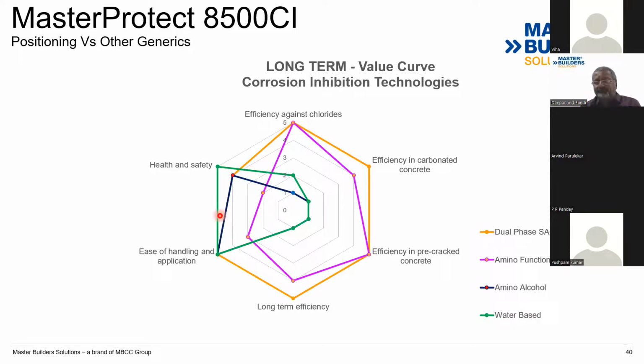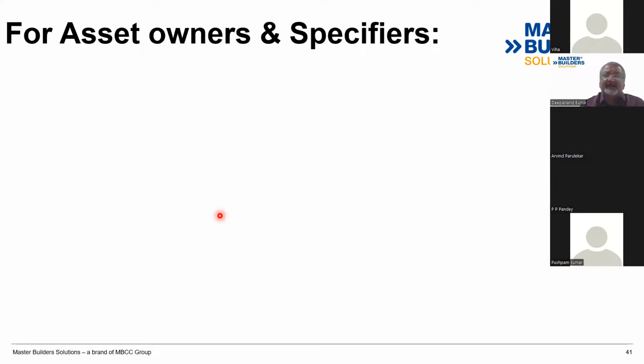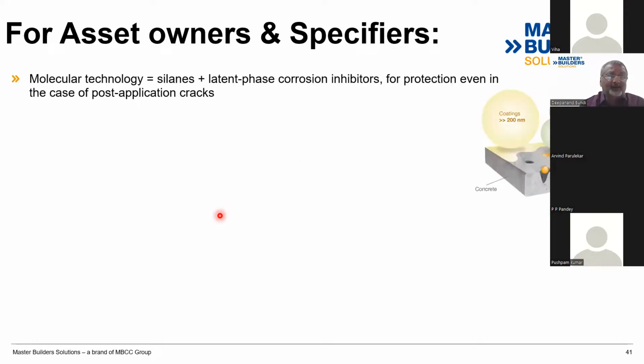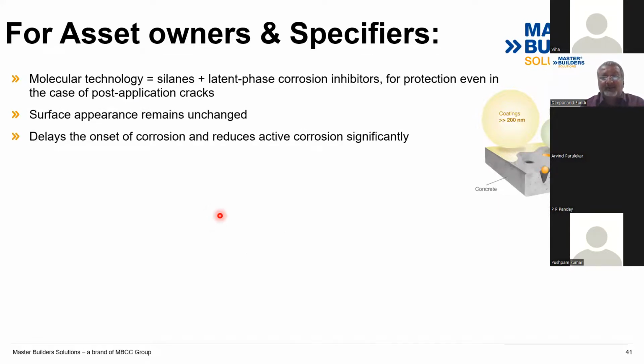And if you look at what the benefits are as a specifier, or as an asset owner, if you have your own assets and you need to protect them, the important highlights for the product are, because they are nanomicrons, they penetrate very easily, and the silanes will give you water protection, water repellency. The surface remains unchanged. It delays the onset of corrosion and reduces active corrosion very significantly. You can see the half cell potentials at the same point have reduced drastically after the application. They are effective against chloride and carbonation.